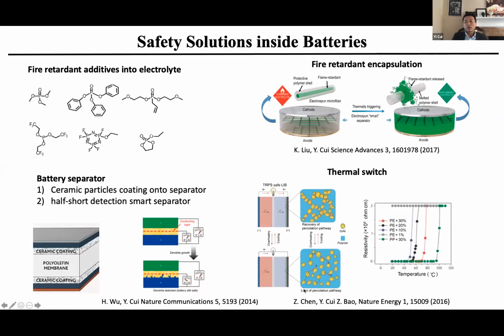So we also consider adding something like a thermal switch onto the electrode coating. This is in collaboration with Zhenan Bao at Stanford right here. If the temperature goes up, this coating layer goes from electrically conducting, metallic conduction, to a pure insulator. This is 8 orders of magnitude resistance change and shuts down the electrical conducting pathway so you cannot release the electricity right there, so avoiding the fast heat-up of the batteries. So I believe more innovations are needed to enhance this thinking on thermal triggers of battery safety concerns.